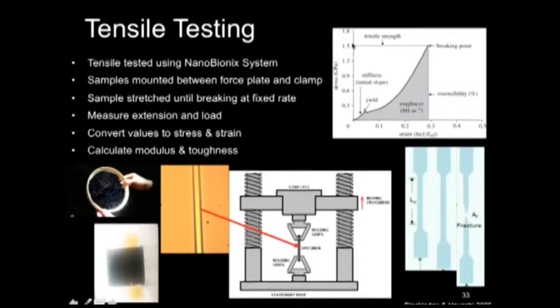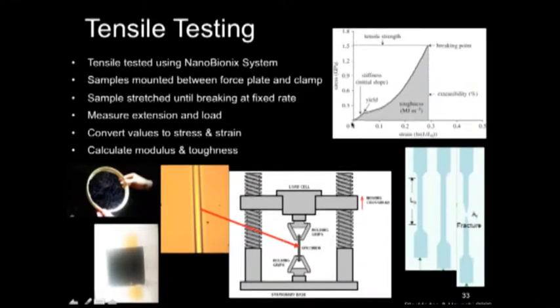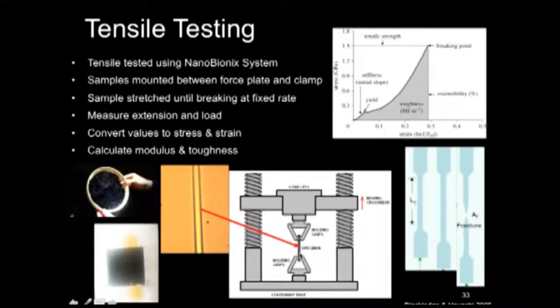As I showed you before, the goal is to measure tensile properties. And these are very typical stress strain curves, like I talked about a little bit earlier, but we also can measure stiffness, which is this initial slope of the stress strain curve. Where the slope changes is the yield point. And again, stress and strain, just to reiterate, the y-axis is strength. It's indicated by where it breaks on this y-axis, and then how far it stretches is the extensibility. It's a measure of stretchiness.